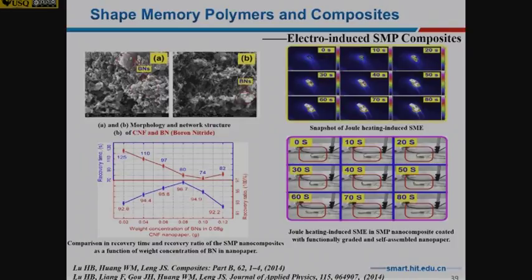We also tried different conductive particles, like carbon nanofiber plus boron nitride. The reason we use boron nitride is that it has very good thermal conductivity. With this one, you can see the sample can deploy from 0 seconds to 80 seconds very easily.